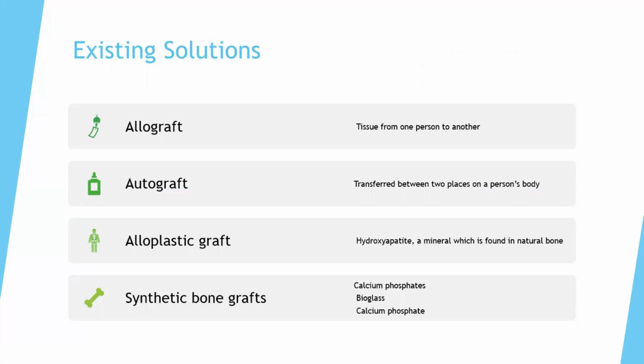Alloplastic grafts are typically comprised of hydroxyapatite, a mineral which is found in natural bone, therefore giving it the ability to mimic bone, giving it an excellent acceptance in the body. This acceptance allows for the alloplastic graft to have osteoconductive abilities, and the synthetic bone scaffold is manufactured using bioactive glass to have similar hardness to that of natural bone. Synthetic bone graft variants can also be created using ceramics such as calcium phosphates and bioglass. These materials are desirable as bone grafting substitutes for their bioactivity and ability for enhancement via doping with growth factors.